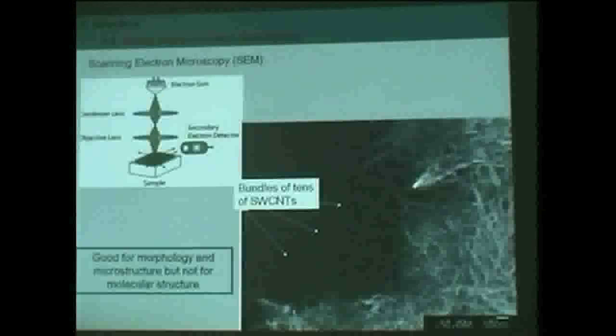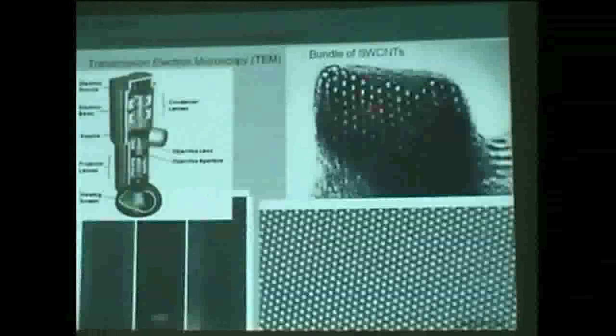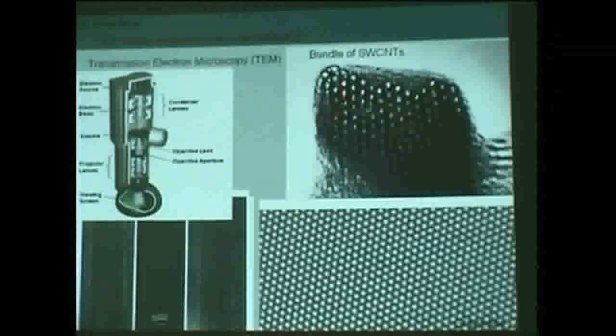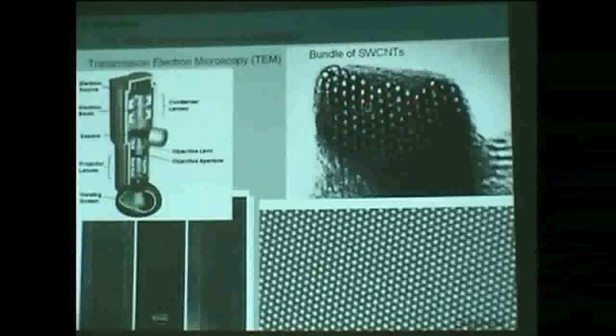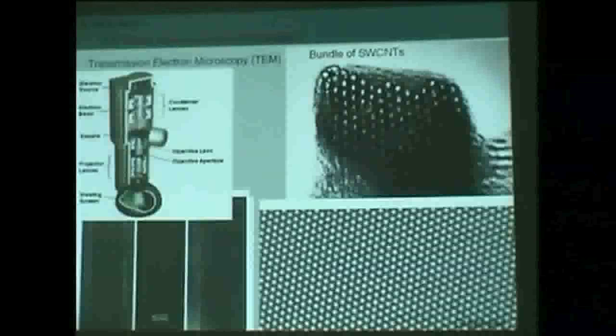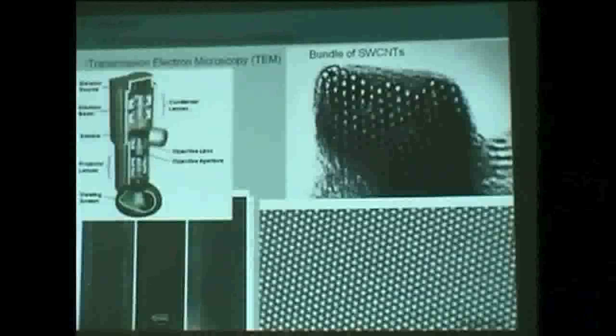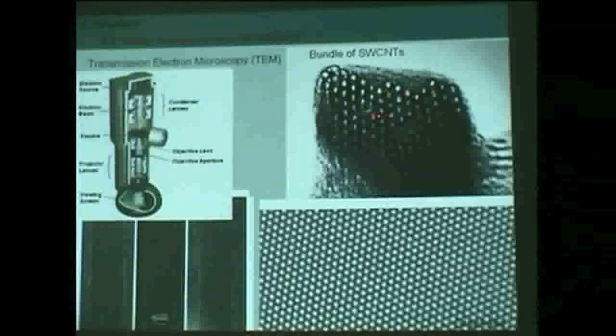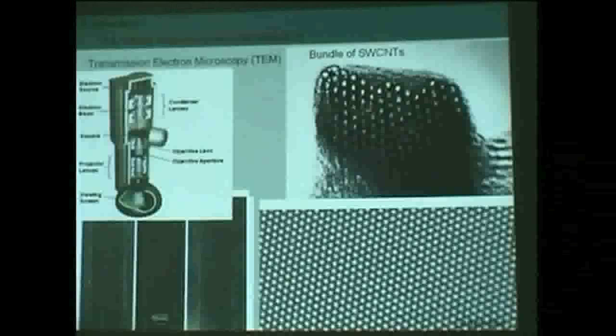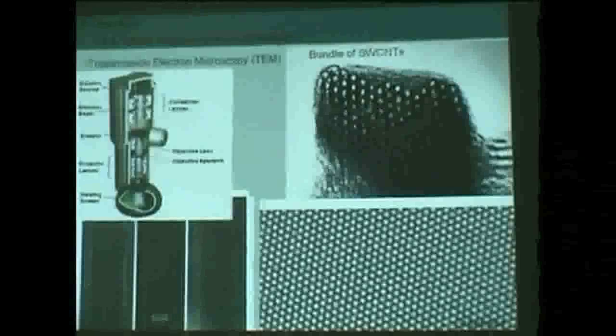These wraps have some crystal structure - you observe a hexagonal network, with translational symmetry between this bundle of strings. So here you understand this is a cross-section of a bundle. Up to now we saw the bundle from the side, and now we look at those tubes from the face, like a cross-section. We observe that they're packed in a hexagonal network, and we confirm that they are tubes - the section is a circle.